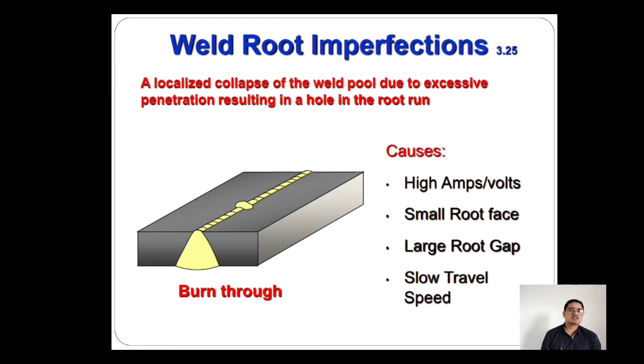So friends, this is burn through. Many of my friends know about burn through. Burn through is basically a localized collapse of the weld pool due to excessive penetration, resulting in a hole in the root run. This may be caused by high amperage and voltage, small root face, large root gap, and slow travel speed.